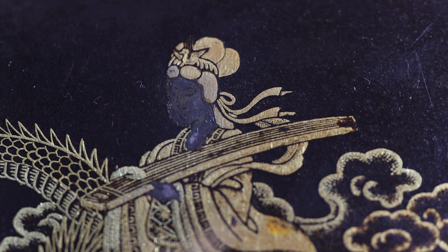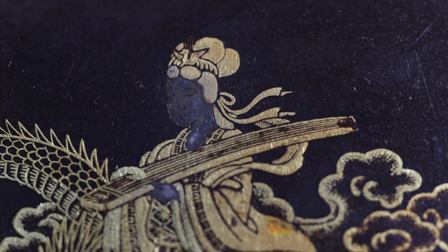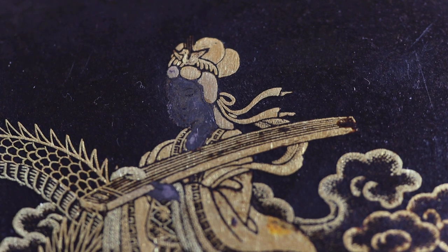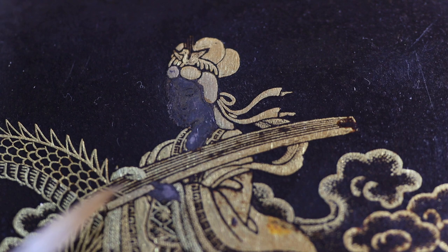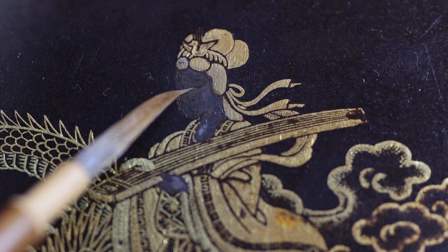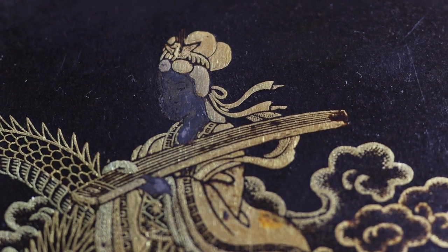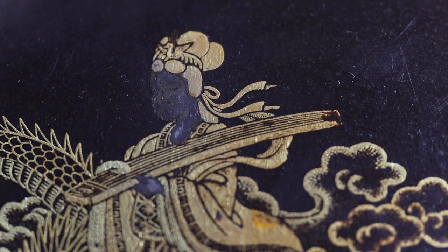Silver is very prone to sulfurizing, and in so doing the silver is being consumed. When you clean off the silver sulfide, it's effectively rusted away — which is why often in work like this, the silver is fugitive and just gone missing. I'm hoping there's enough here. I can see the eye and the eyebrow — it's ridiculously finely done. These men were just insane.